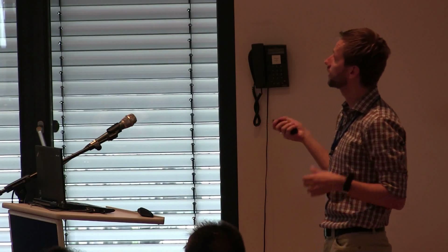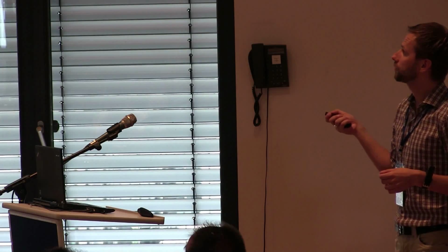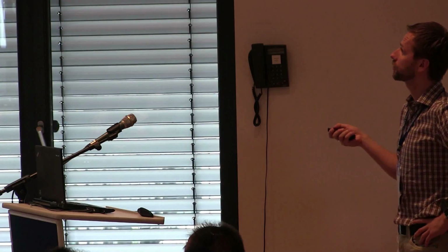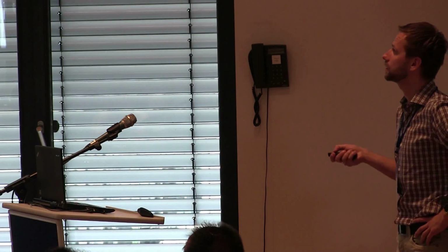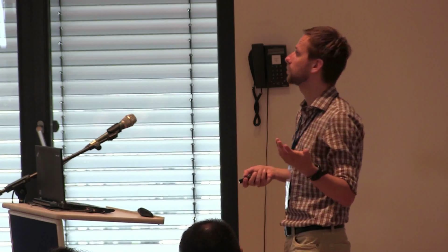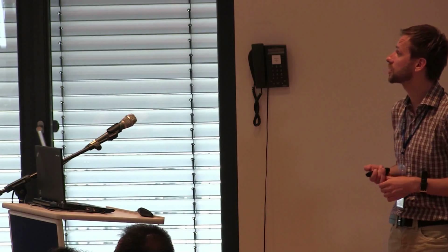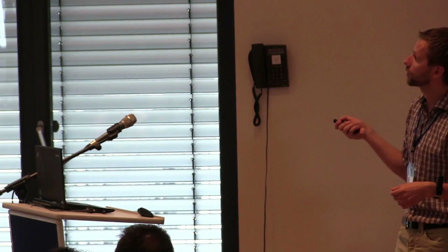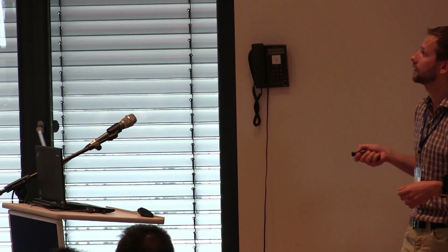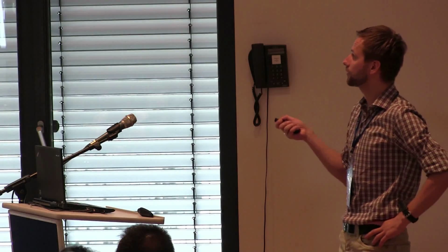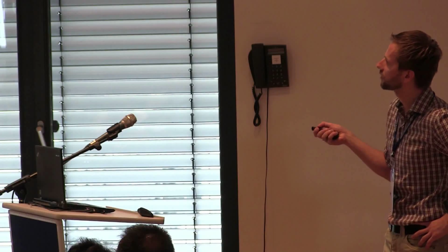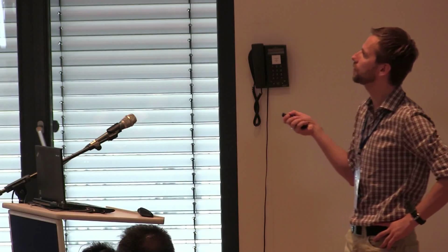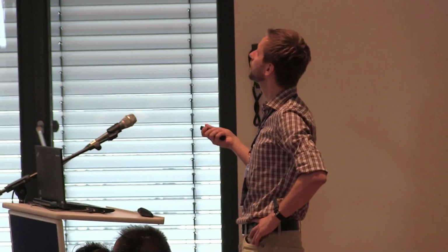All right, so these are the insights of our model. The input parameters are the measured experimental Terahertz waveform, and then the starting conditions for graphene, the Fermi level, and the momentum scattering time at the Fermi level, which you know from the linear characterization from Raman spectroscopy. Those are the only input parameters. Then you can propagate the experimental Terahertz pulse through graphene numerically, and you will get the numerically transmitted waveform. And now we can emulate the experiment, so we have the measured incident waveform and then the numerically transmitted one, and then we can compare it to the real data, and this is how it looks.